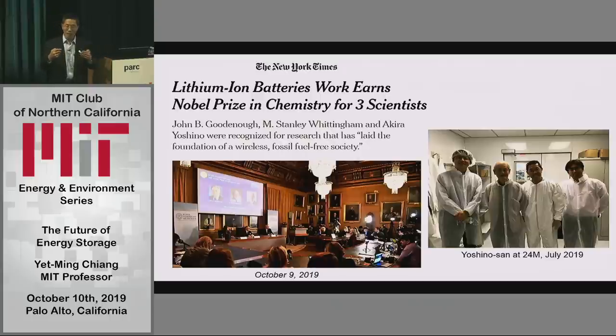So a lithium metal battery is an electroplating machine. Every time we charge and discharge it, we plate lithium metal. And so what he did was to show that you could use graphite and not actually get the metal. So the irony of all this is that what Stan Whittingham did ran into this obvious barrier with lithium metal. In the interim, lithium ion was created. John Goodenough's contribution, amongst many, was to come up with that lithium cobalt oxide that I showed you earlier. But here in 2019, we're back to lithium metal again.